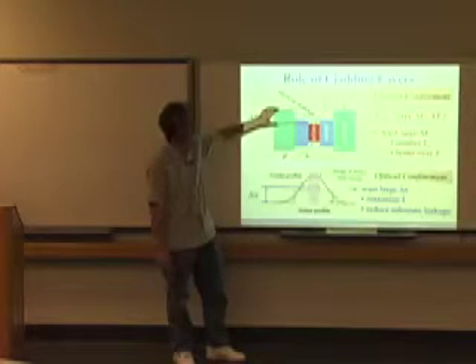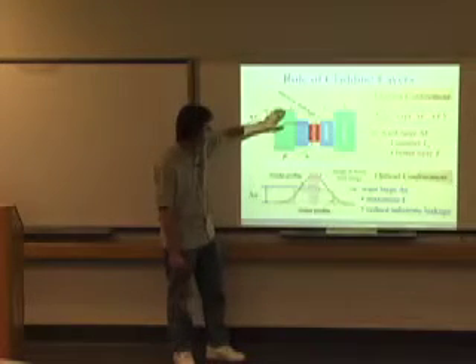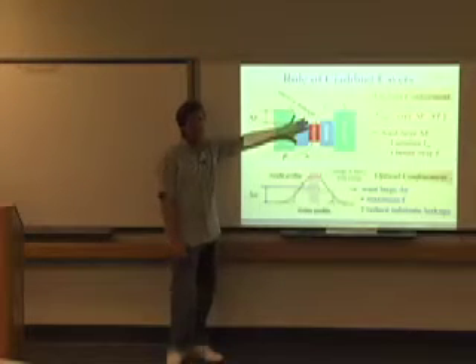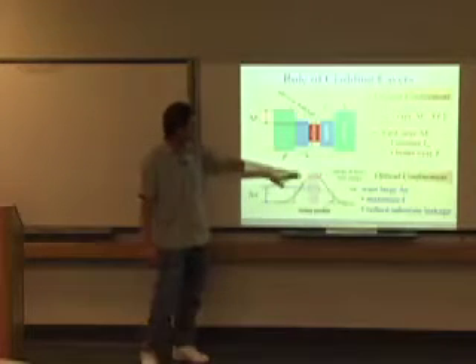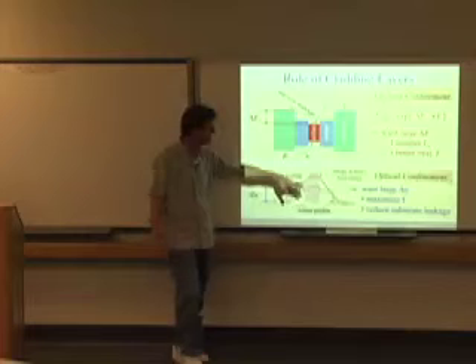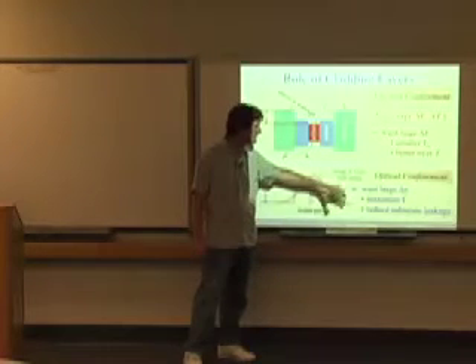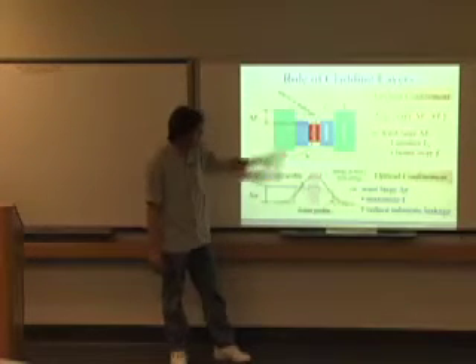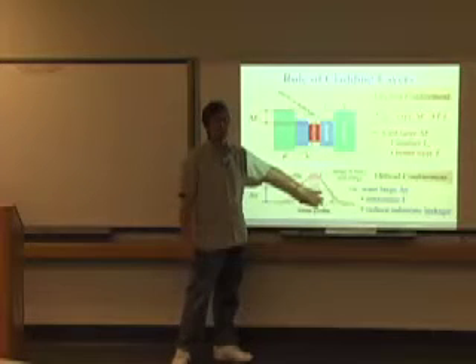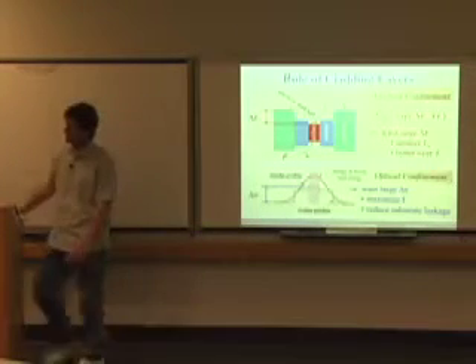So you want a very large band gap offset here. So for that, you really need a higher band gap cladding layer. In addition, you want to have good optical confinement. Again, something that's not really a requirement for LEDs, but for lasers, you need to have a good vertical confinement. So you again want a low index cladding layer to confine your mode nicely.